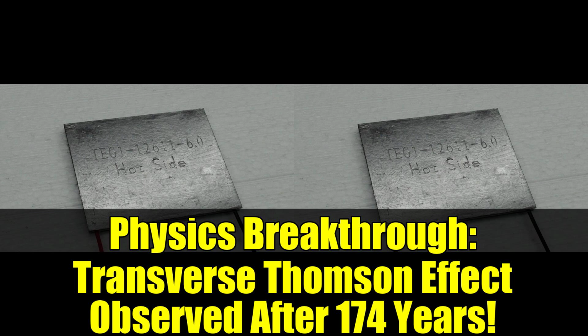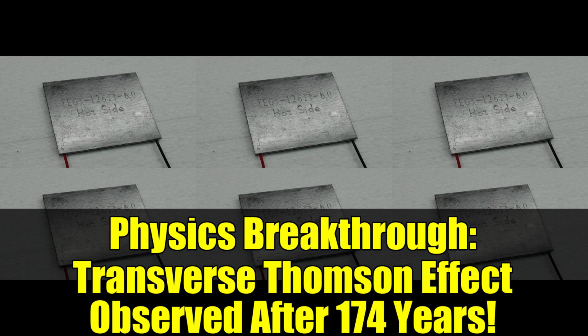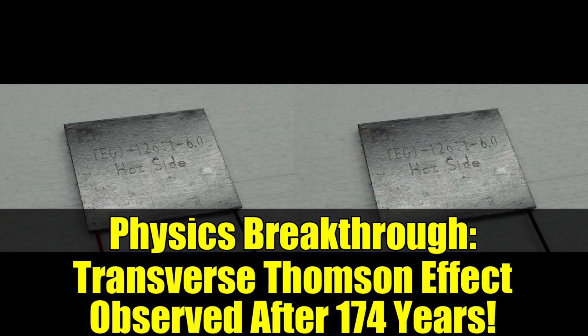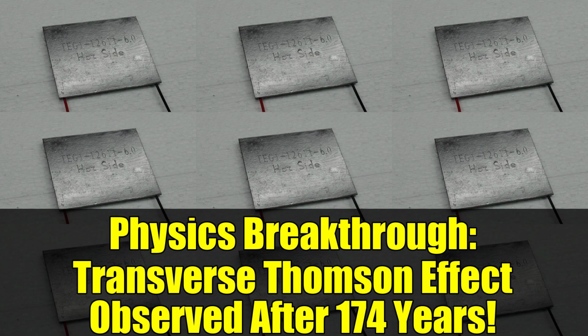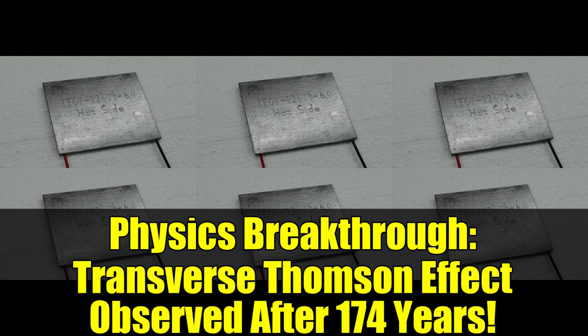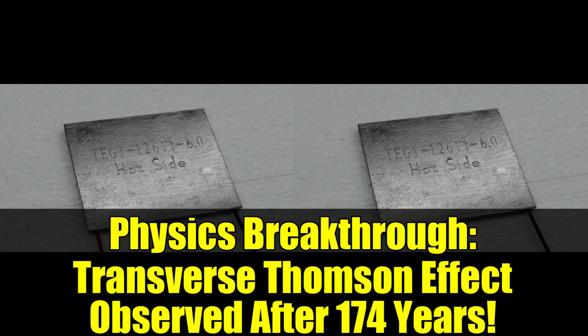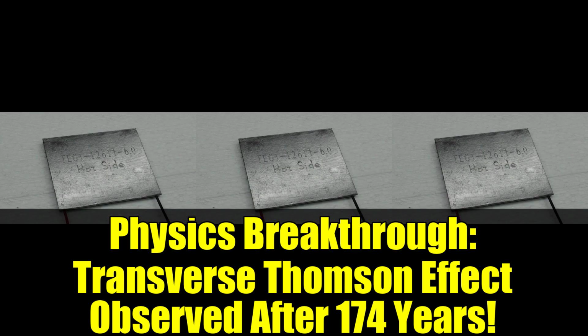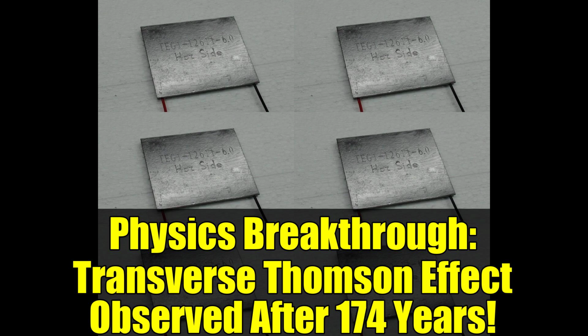Innovative techniques for measurement. To overcome the challenge of signal isolation, the Japanese researchers employed an infrared camera to monitor the thermal response of the sample when a periodic electric current was applied. They explained, "By extracting the temperature modulation component that oscillates at the same frequency as the applied current from the thermal images, we successfully isolated the thermoelectric signals from the Joule heating."